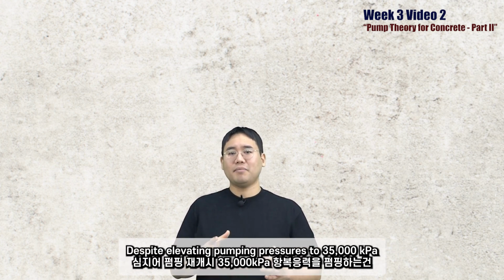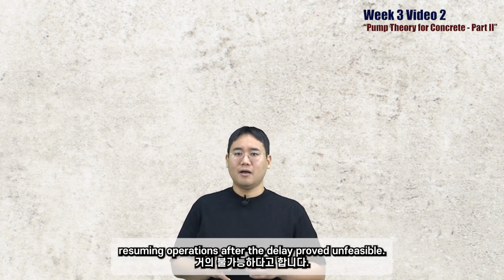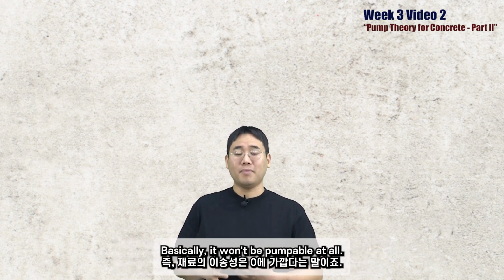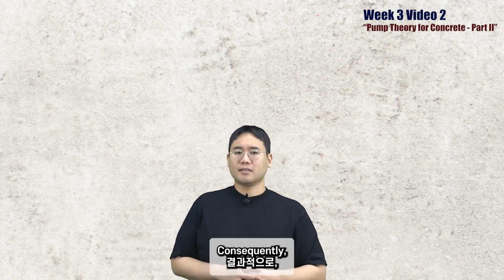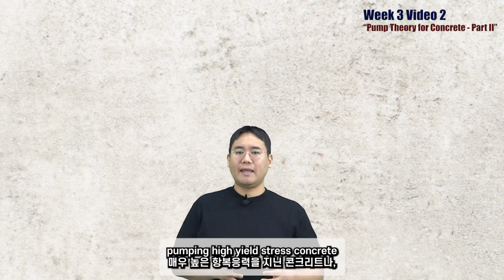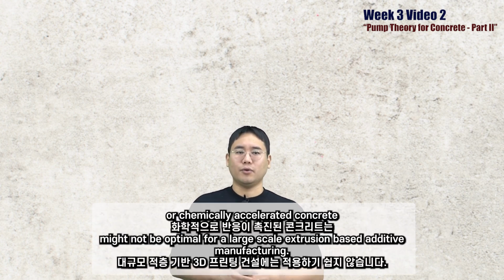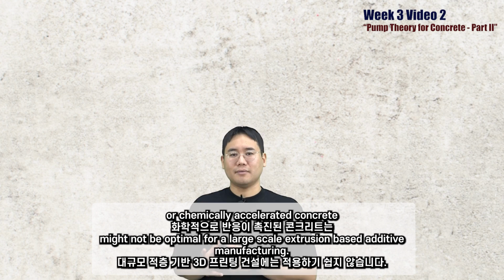Despite elevating pumping pressures to 35,000 kilopascals, resuming operations after the delay proves unfeasible. Basically, it won't be pumpable at all. Consequently, pumping high yield stress concrete or chemically accelerated concrete might not be optimal for large-scale extrusion-based additive manufacturing.